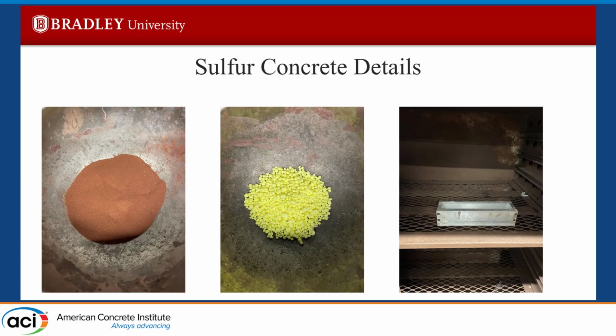So let me get into the details of what the sulfur concrete is made of. In the first picture on the left, you'll see Martian soil, which is approved by NASA. They have taken soil from Mars itself and replicated it here on Earth for use in experiments, so that we don't have to constantly keep going back there to get testing materials. And in the middle there, we've got solid sulfur, which is just sulfur itself. The process is different than regular concrete. We actually have to melt the sulfur down to its liquid form and combine it with the Martian soil, unlike regular concrete. In this case, we're using 50% Martian soil by volume to 50% sulfur by volume.